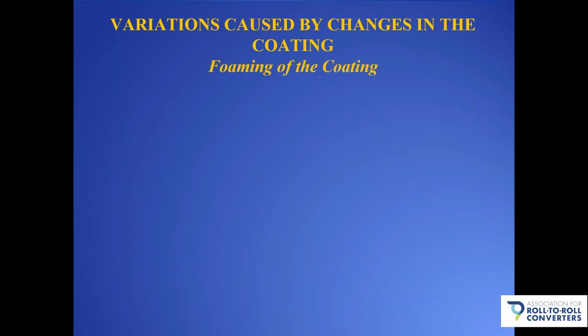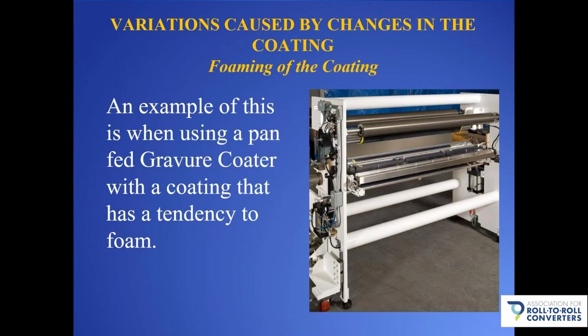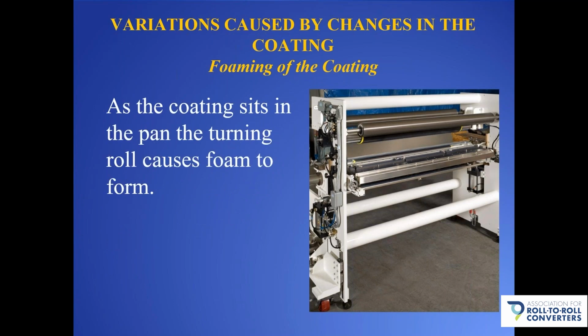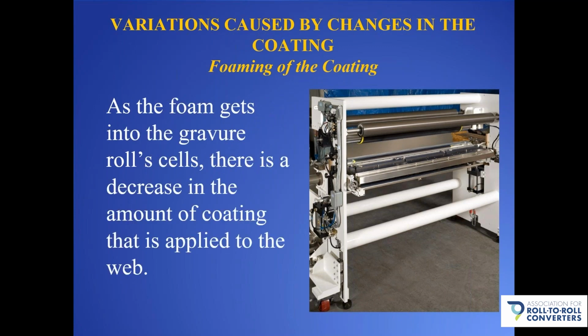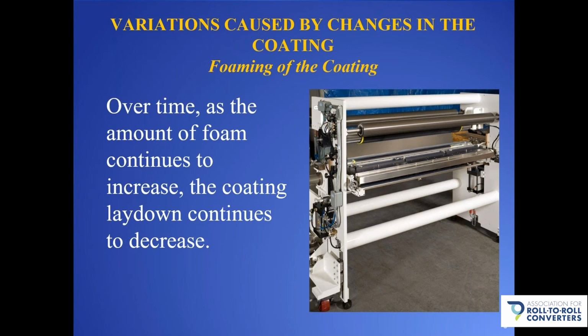So next, let's talk about foaming of the coating. An example of this is when using a pan-fed gravure coater where the coating has a tendency to foam. As the coating sits in the pan, the turning roll causes this foam to form. And as this foam forms, it gets into the gravure roll cells, which results in a decrease in the amount of coating which is applied to the web. And over time, as the amount of foam continues to increase, more foam gets into the cell, less coating therefore gets into the cells, and the coating laydown continues to decrease.